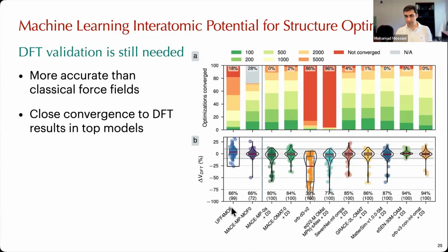You can see that the classical force fields are not great. The fine-tuned machine learning potential is doing okay and actually pretty good. But some of these machine learning potentials, like ESEN, are getting very accurate. And this also shows in how many steps of optimization you converge to the final solution. So you see that these machine learning potentials are actually very powerful now for doing optimization of crystal structures.